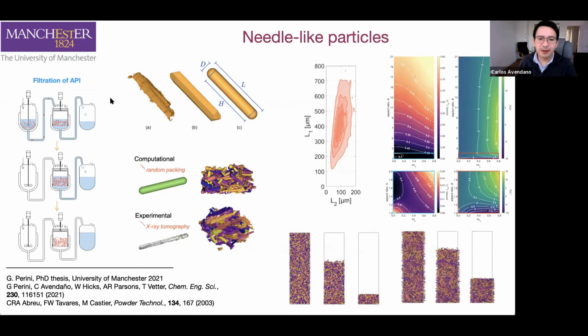So from the experiments, we have these types of populations for different experiments. Some of them run at different temperatures, some at different pressures, and so on. We wanted to have a quick technique to determine, for a given size and shape distribution, what porosity we have. And we would like a technique where we could easily manipulate that size and shape distribution to find the optimum parameters to maximize the porosity of the system. So that's the problem: given a certain distribution, what will be the porosity that we will get?